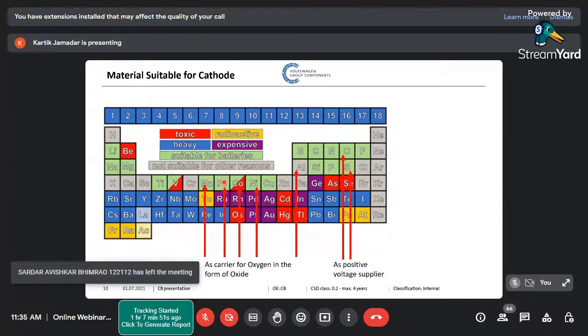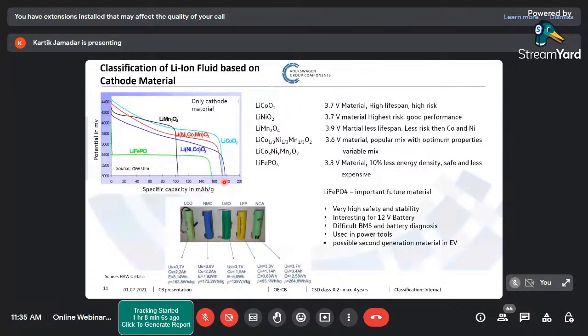So there is always some kind of compromise, but still I believe that for the Indian market and for a lot of other places, LFP could be a very good alternative because of the raw material abundance which is available and the price which is quite interesting. So this is about the different kinds of cells. They are all working on the same principle, which we call lithium ion technology. NCA, nickel cobalt aluminium; LFP, lithium iron phosphate; LMO, lithium manganese oxide; NMC, nickel manganese cobalt; LCO, lithium cobalt oxide. Each has its own advantages and disadvantages.